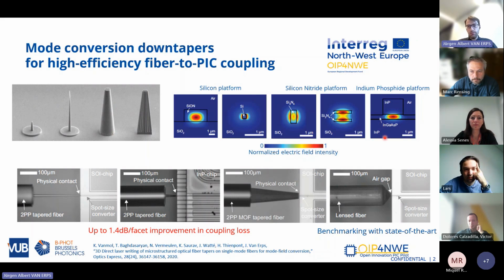And within OIP4NWE, we're focusing on indium phosphide waveguides. And there you see that the mode field diameter will be close to 1 micron. So you have a 10 times mismatch between the mode field diameter in the fiber and in the on-chip waveguide. This mode field diameter mismatch typically means that you have some losses when you're connecting the fiber to the chip.